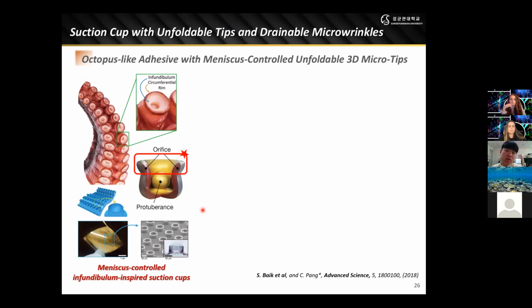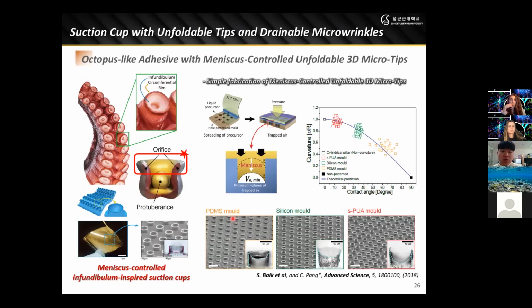The bio-inspired synthetic adhesive is fabricated by simply controlling the meniscus of a liquid precursor during a molding process. It does not involve any hierarchical assemblies or additional surface treatments. The various micro suction cups having different curvature can be fabricated by changing the micro hole pattern board because their surface energies are different.